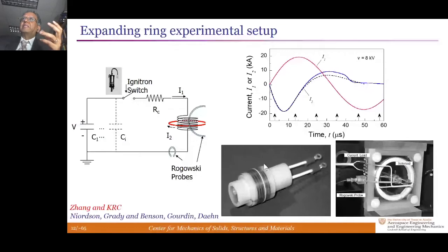The coil itself is held fixed inside a very stiff housing, so it doesn't have the ability to move. But the specimen is free, and so it wants to get away from the coil, and it expands out radially, symmetrically. In timescales of 10 to 50 microseconds, the object strains to strain levels on the order of 20 to 30%. Strain rates are on the order of 10³ to 10⁴ per second. The important thing is it's a body force loading. There are no stress waves necessary to generate the modes.